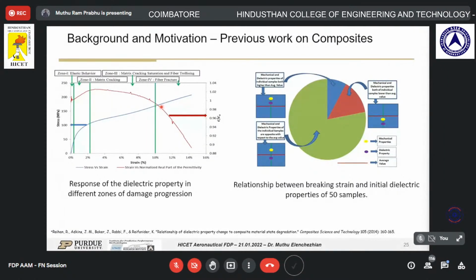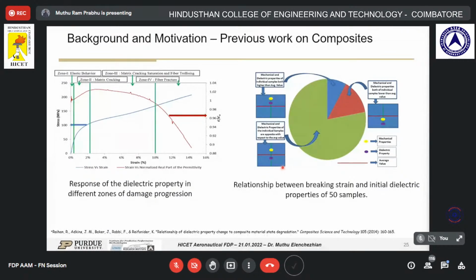This test was done on about 50 samples. On most of these 50 samples, what was observed was that if the mechanical property, that is the strength of the material, was higher, then the dielectric property observed was lower. This is compared to the average values of the mechanical properties and dielectric properties.